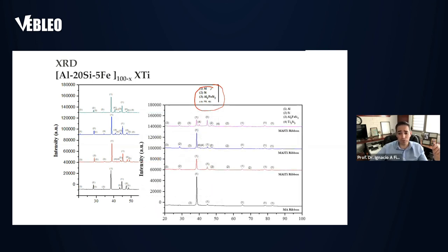Moving to the ribbons, most of those peaks already seen for the ingots disappear. We only found aluminum, silicon, and the intermetallic — which is quite stable, that's why we found it here. Although it's one small peak, it's consistent — it basically matches at these angles. That's why we thought it was the same intermetallic already shown for the other alloys.